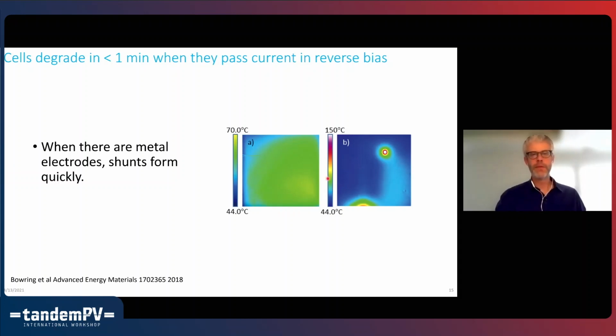With metal, it's just astonishing how quickly the solar cells degrade. We believe metal punches all the way through the solar cell. If you use thermal imaging after you've operated the cell in reverse bias, you see very small hotspots, which is almost certainly where metal is going through the device. So pretty early on, we just stopped using metal, and you know, my group has always been a big believer in ITO electrodes anyway, for the reasons I said earlier.